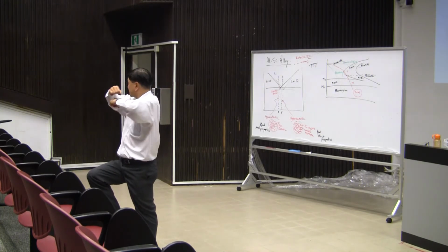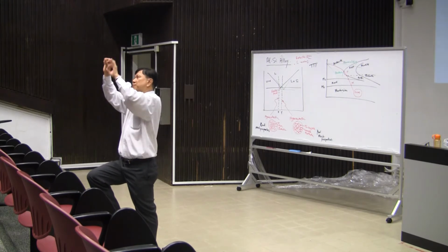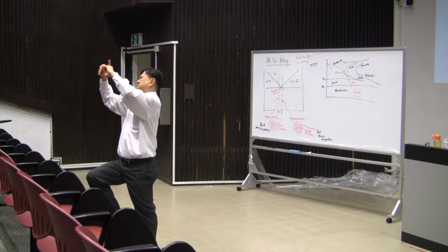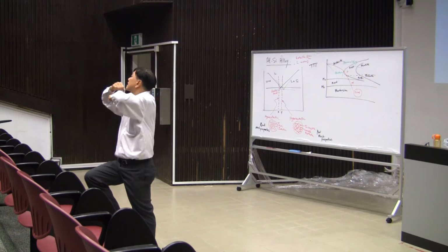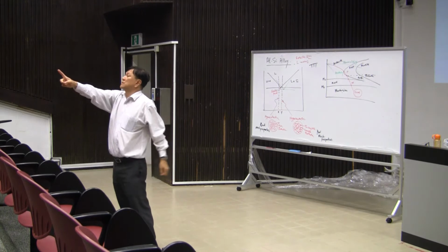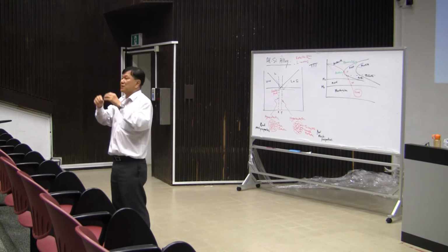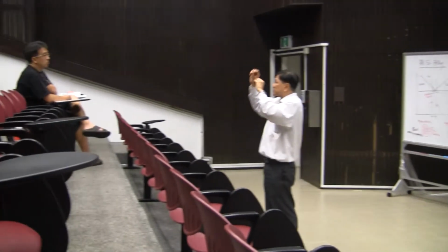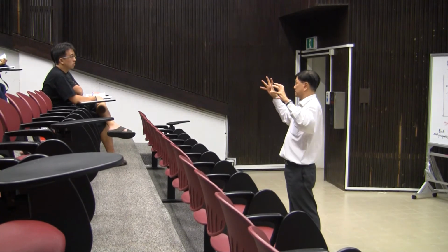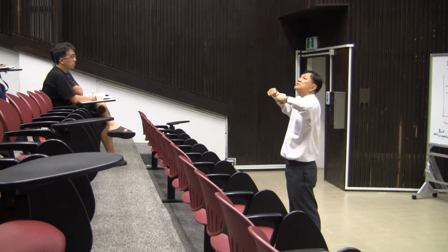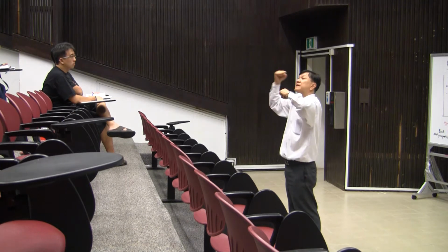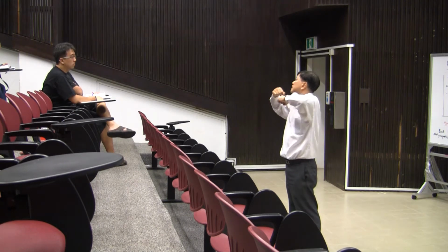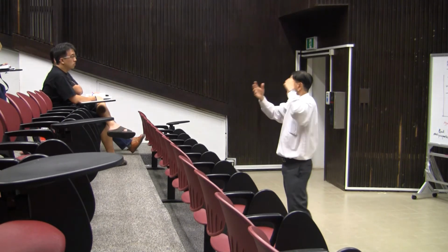Dislocations can take place very easily. But if my crystal like this becomes distorted, then it will not slide so easily. So in martensite, because the carbon trapped inside creates a lot of what? Distortion. Then it becomes very difficult to slide. Then your material becomes very strong, difficult to deform. Alright? Okay?